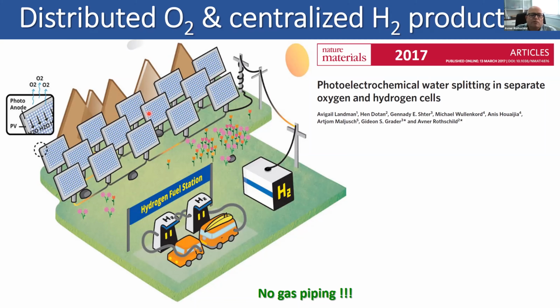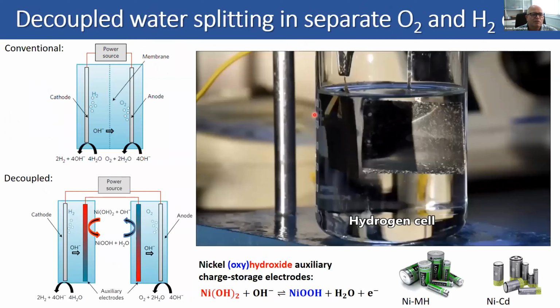So to collect all the cathodes from all these millions of cells and put them together in a big reactor that produces hydrogen. So schematically, this is shown here. And that, of course, would solve the problem of the gas collection from these millions of cells in the solar field. So that was the idea. And we found a solution for this, perhaps not an ideal solution, but a solution. And the solution goes like this.